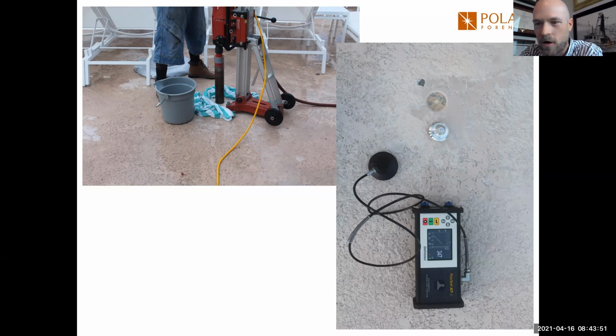So this involves gluing a steel puck to the surface and then connecting it to this device that applies a tension force until that puck essentially fails. And this provides us with a couple key pieces of information. It lets us know what the adhesion strength is of these materials. And it also lets us know that when it does fail, where does that failure occur? At what layer?